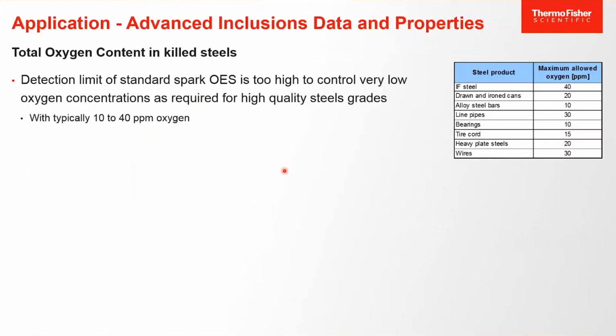I mentioned total oxygen content. With Spark optical emission, inclusion analysis offers a very interesting possibility to determine extremely low levels of oxygen, which are typically not possible with the standard calibration method. Examples of types of steel where oxygen has to be measured at very low concentration are given in this table. So typically, cases where oxygen is around 10 to 40 ppm. So normally the detection limit of the instrument does not allow measuring that with good precision and accuracy.